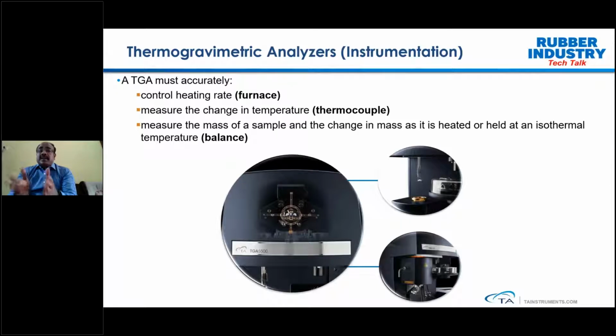One is the furnace. The furnace is the place where you control the heating rate as well as temperature. You maintain a particular temperature, and you can also have atmospheric control. So the furnace is one of the very important aspects. And then comes the change in temperature, which is measured by a thermocouple. And the third, of course, is the balance.